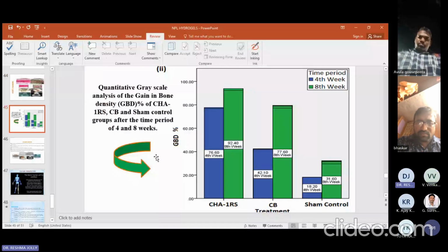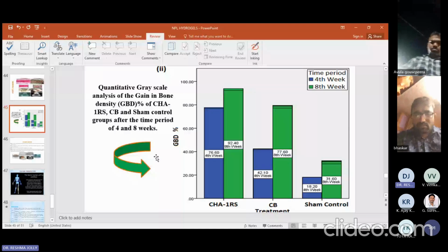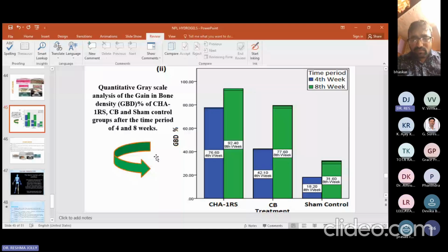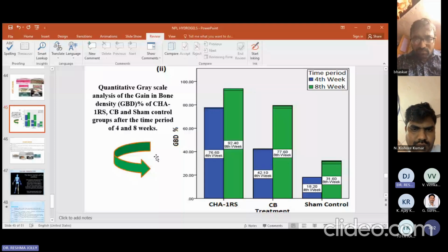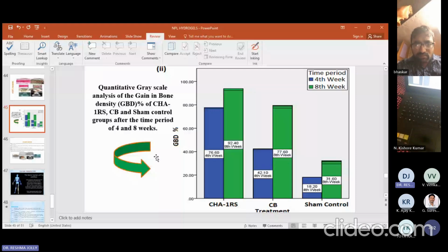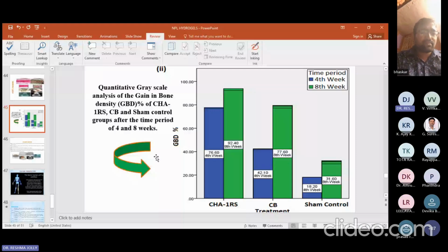Yes, madam, okay, thanks. So, after doing the histopathology and the radiography, we wanted to quantify this study. For that, we performed quantitative gray scale analysis, which is the parameter to see how much gain in bone density there is. We performed this in the civil engineering department of Aligarh Muslim University. Actually, we could have done micro CT, but that was not available at that time, so we were unable to do that. So, gain in bone density, as you can see, for our material at 4 weeks was 76%.